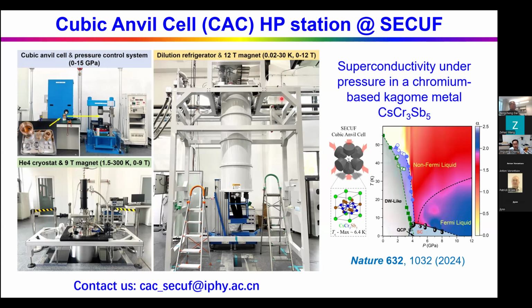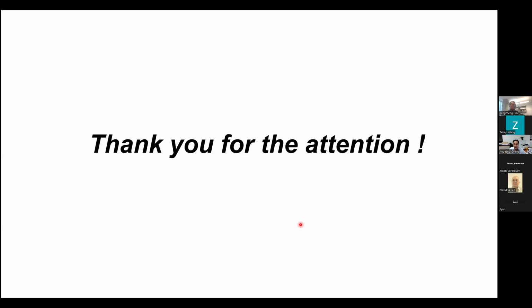And recently, in collaboration with Professor Guanghan Cao, in our cubic anvil cell high pressure station, we found superconductivity in this chromium-based Kagome metal, this 135 phase. So around 4 GPa near the magnetic quantum critical point, we observed superconductivity. With that, I think I will conclude my talk, and thank you for your attention.